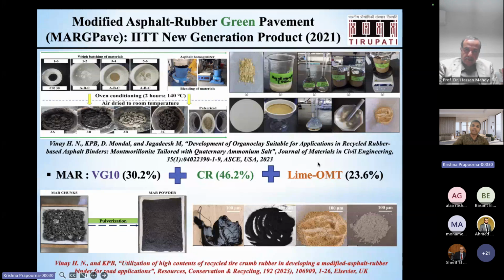Okay, so we actually came up with this product, lime with organo-montmorillonite. So we charged these montmorillonite sections and then clubbed with hydrated lime and then blended that with rubber and base binder, VG10 with rubber and lime OMT that we prepared in our own lab, okay, and run it through drying. That gives us the pulverized, powdered, modified asphalt rubber that could be simply replacing a lot of aggregates that are finer than 4.75. So that means you're also conserving natural resources, natural aggregates, using rubber crumbs.